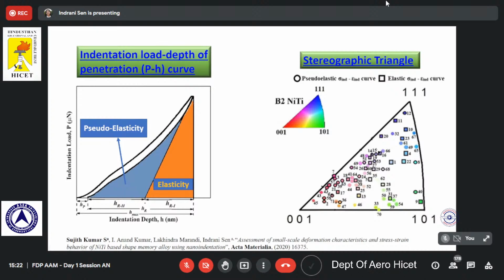And to our surprise, what we found is that when we did this for all the different grains, you can see this is a stereographic triangle, and the colors here signify the color of the grain that we have seen in the EBSD map based on this orientation. So we have indented on several orientations, and we have found that the recoverability of these grains is different. These orientations are different.